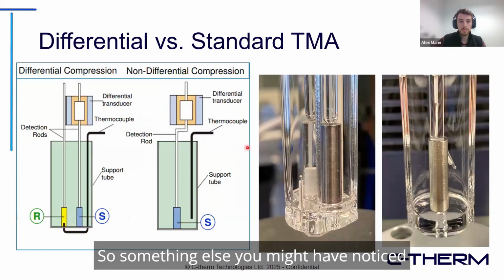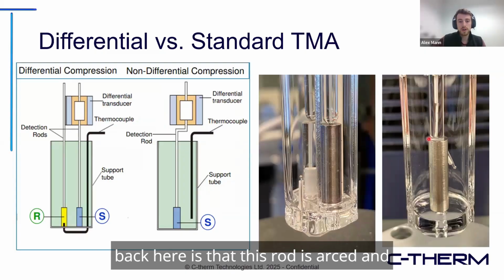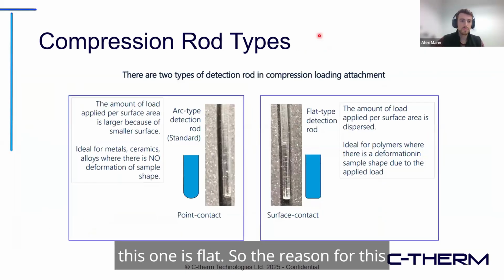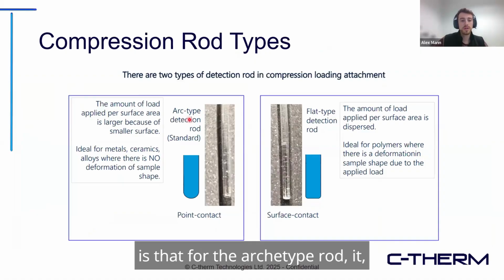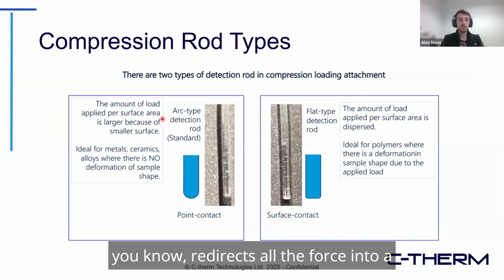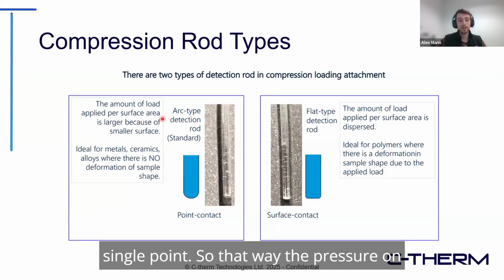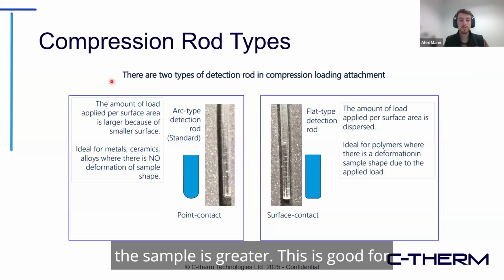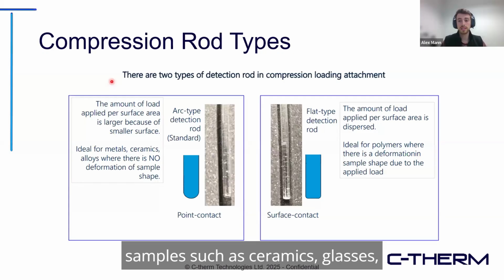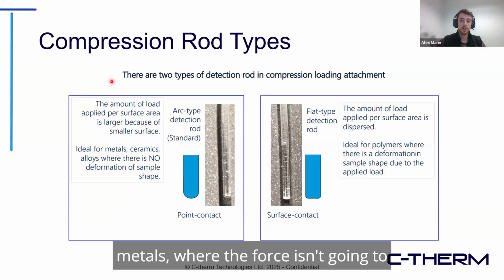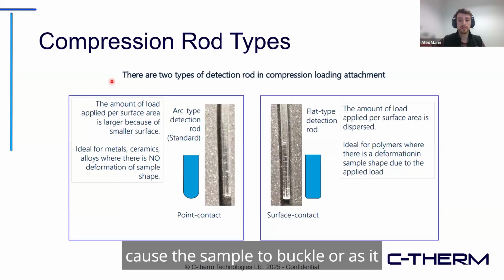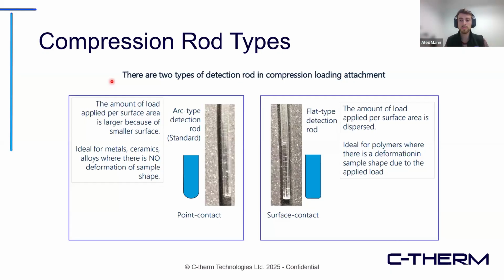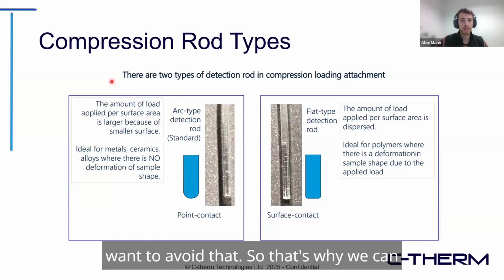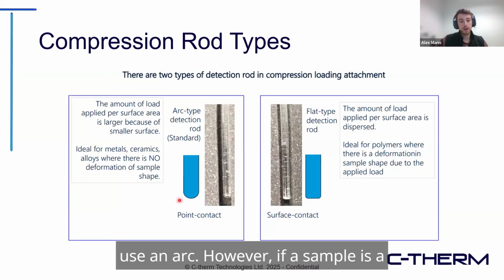Something else you might have noticed back here is that this rod is arced and this one is flat. For the arc type rod, it redirects all the force into a single point, so the pressure on the sample is greater. This is good for samples such as ceramics, glasses, and metals, where the force isn't going to cause the sample to buckle, and as it gets heated up, the sample isn't going to be soft and let our rod penetrate. We want to avoid that. So that's why we can use an arc.